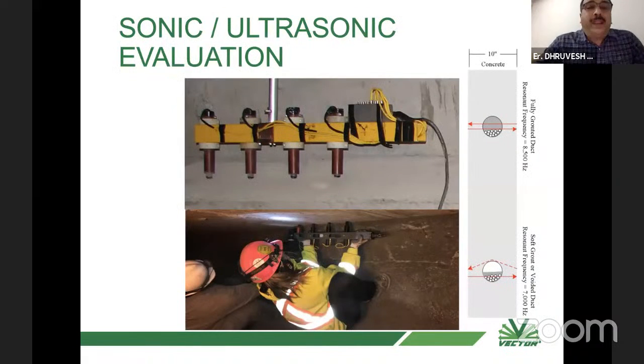You can use this impact echo sonic ultrasonic evaluation method. It is developed by Vector itself, and we use an impact equipment or a probe which impacts, and this four-probe unit will take the readings. The sonic ultrasonic sounds will be received by this probe, and depending upon the frequency we can find out whether voids are there in the tendons or not. If there is a void, then the frequency will be less. It's a different path. If there is dense grout, then the frequency will be higher.